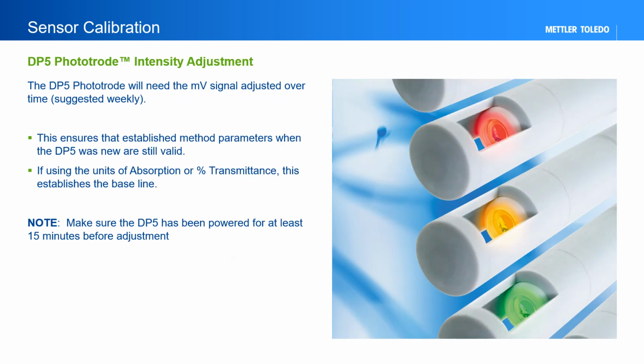The DP5 phototrode will need the millivolt signal adjusted over time. Weekly is suggested. This ensures that established method parameters when the DP5 was new are still valid. If using the units of absorption or percent transmittance, this establishes the baseline. Please note and make sure that the DP5 has been powered for at least 15 minutes before adjustment.